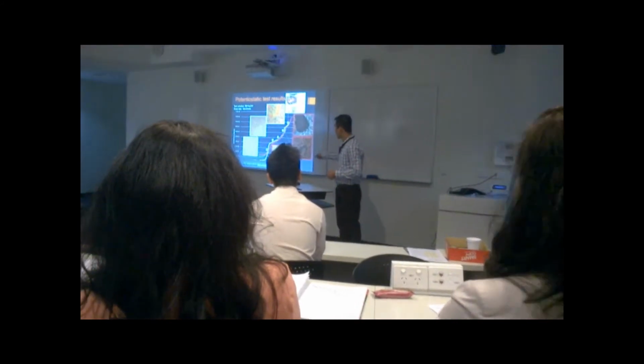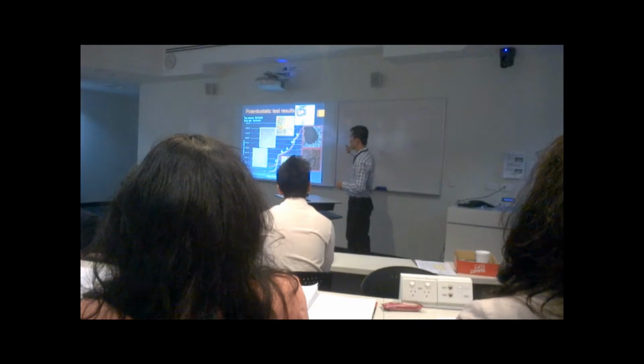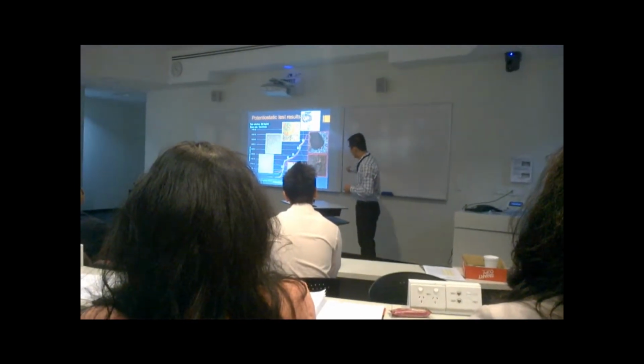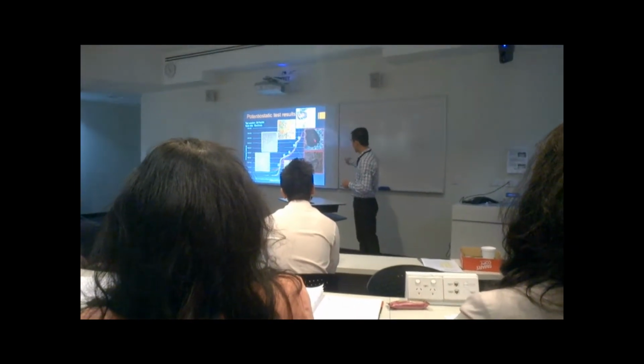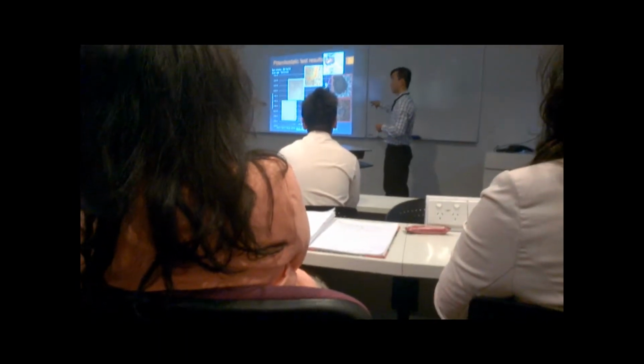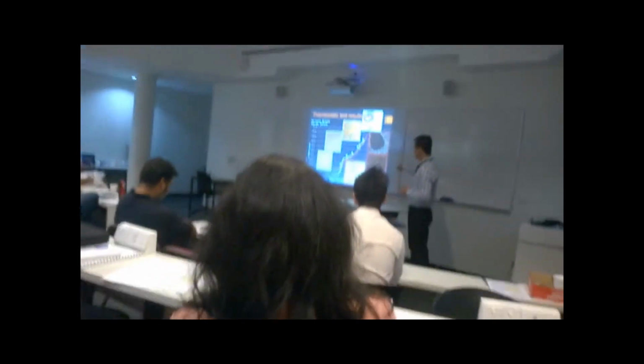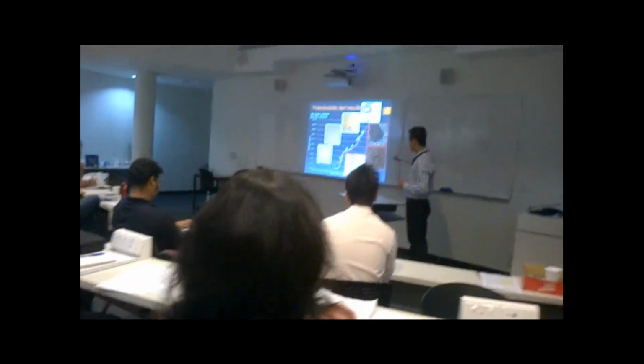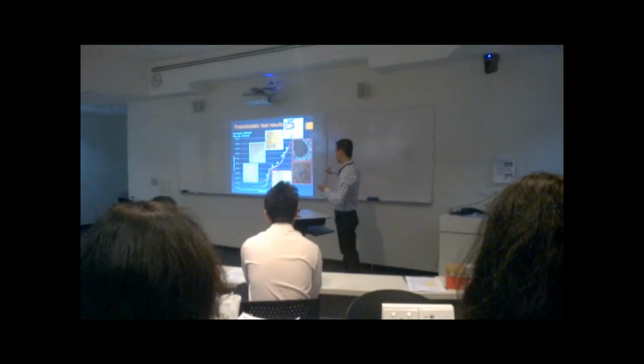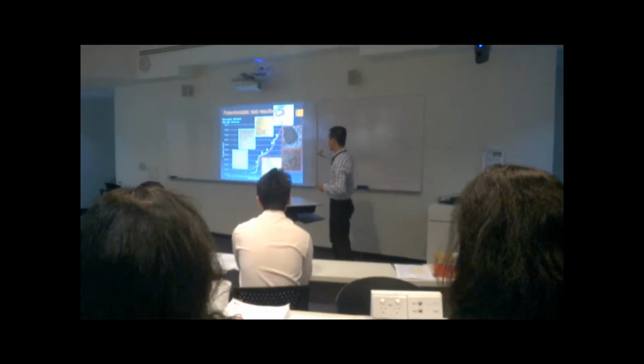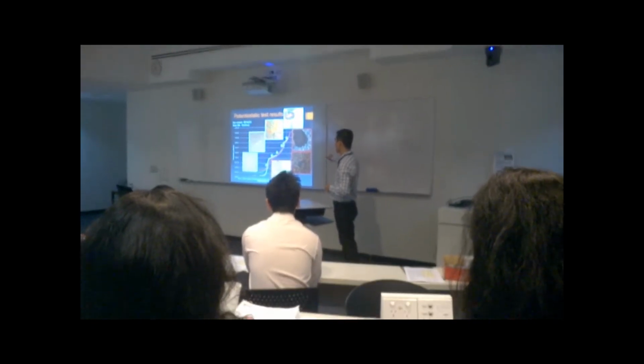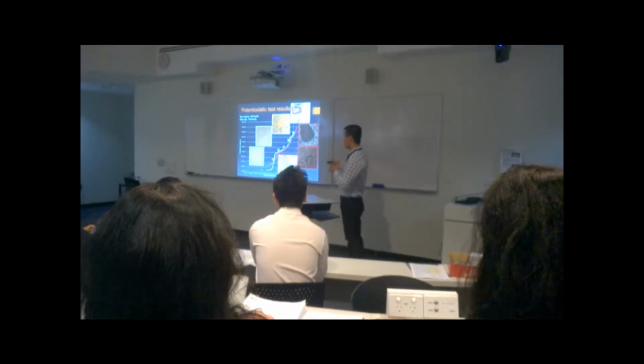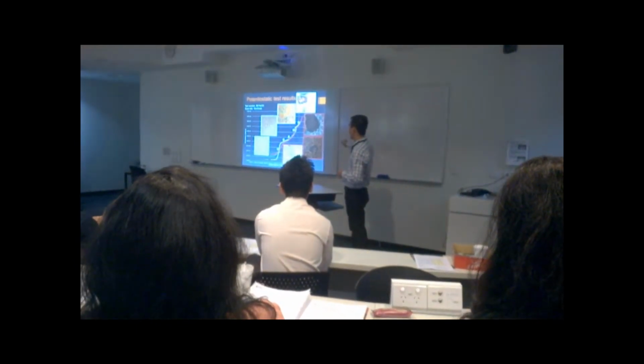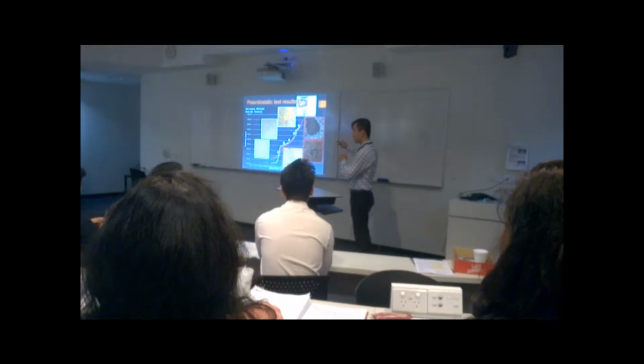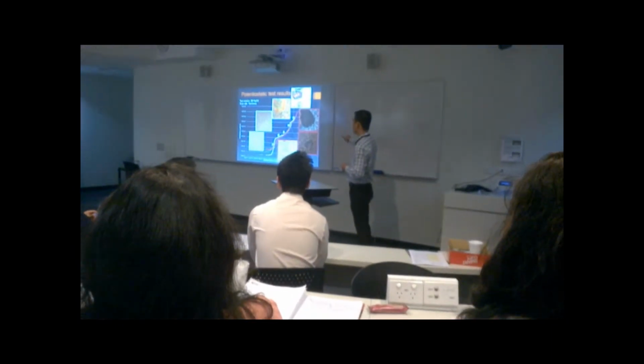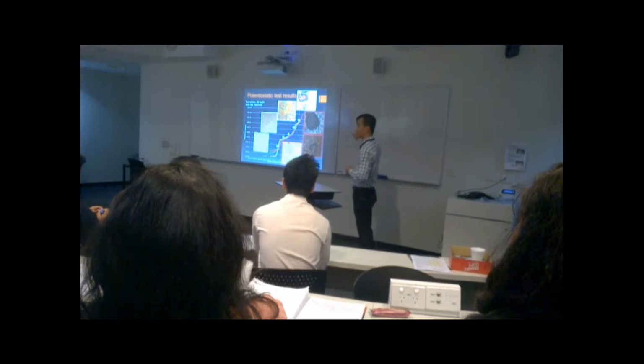All the pictures above the curve are for the metal with an austenitic matrix, and all the micrographs below the curve are the martensite matrix. So basically, what it gives me is that at the first potential, you can see that no corrosion happens on the surface, on either the matrix or the carbide. When it increases to the second potential, for the alloy with the austenitic matrix, the carbide particles are dissolved. And further increasing the potential shows that the carbide is starting to dissolve before the matrix.